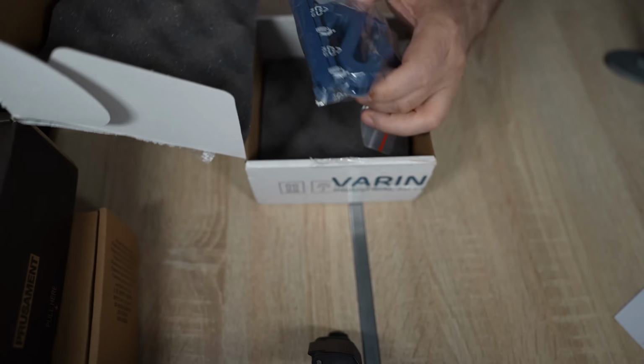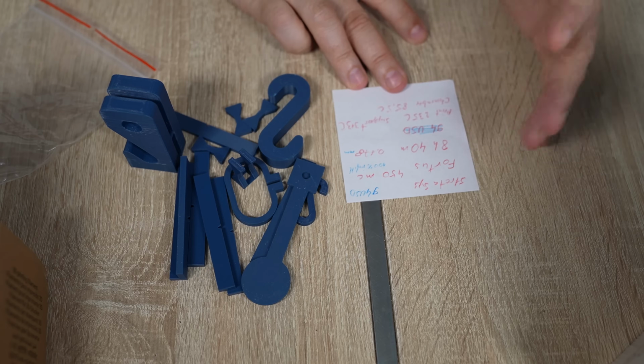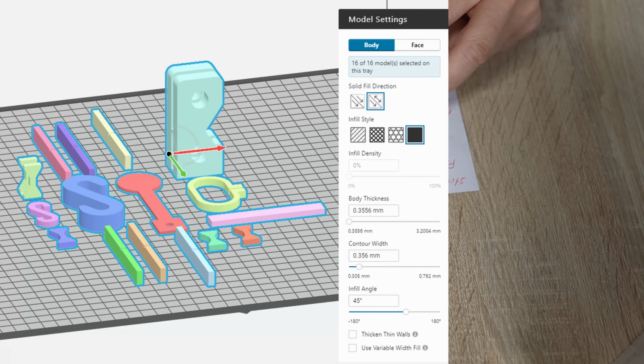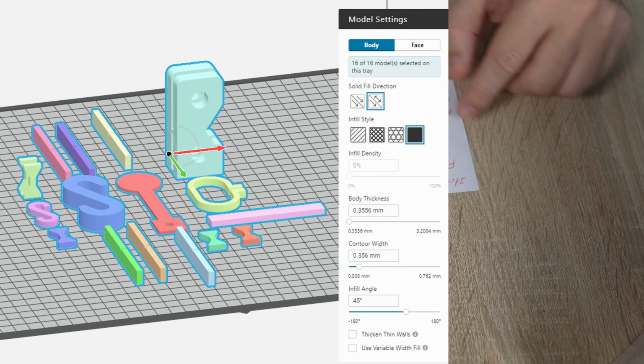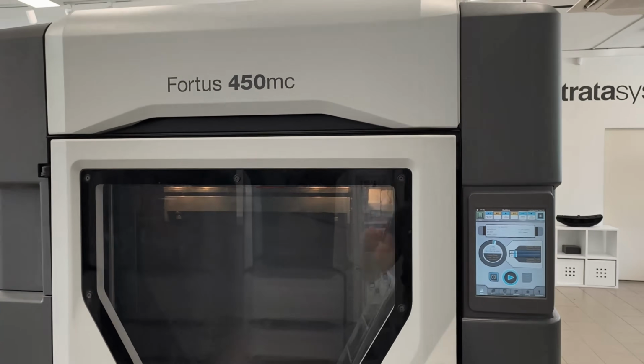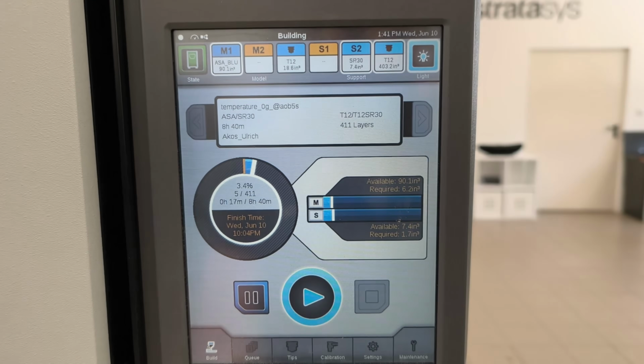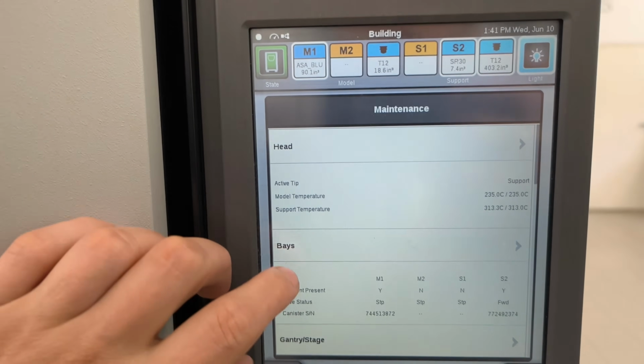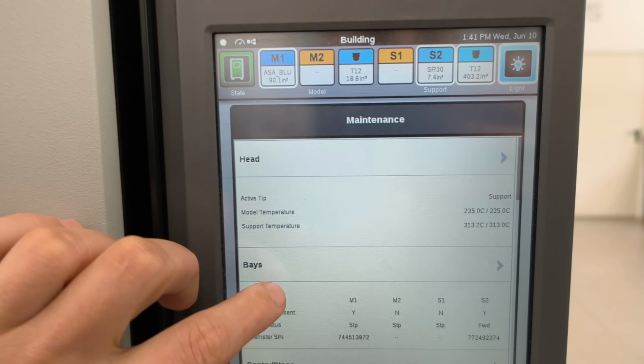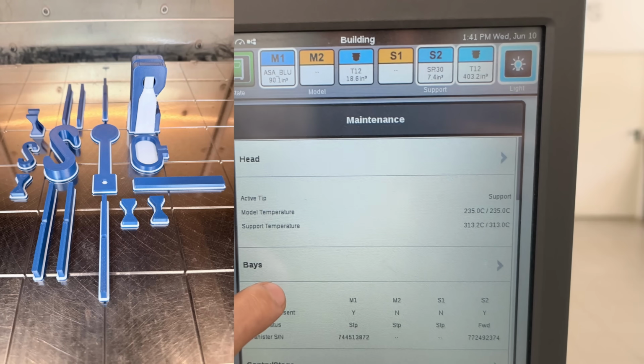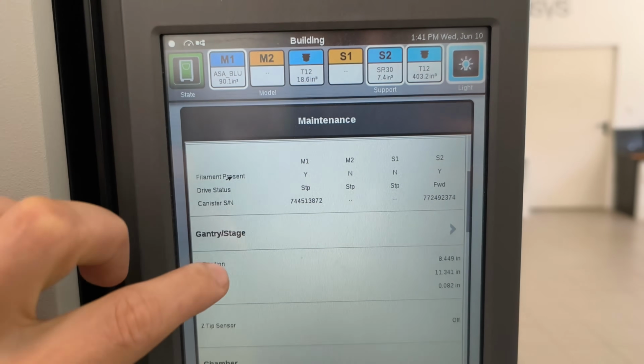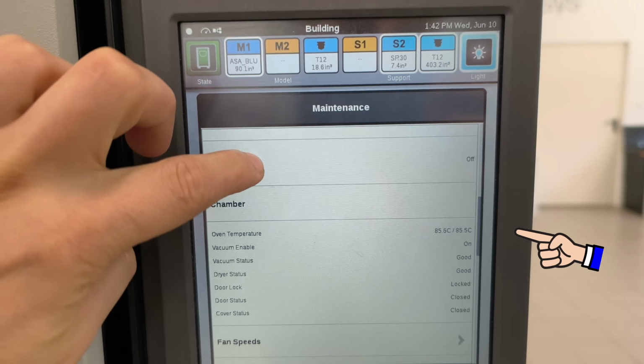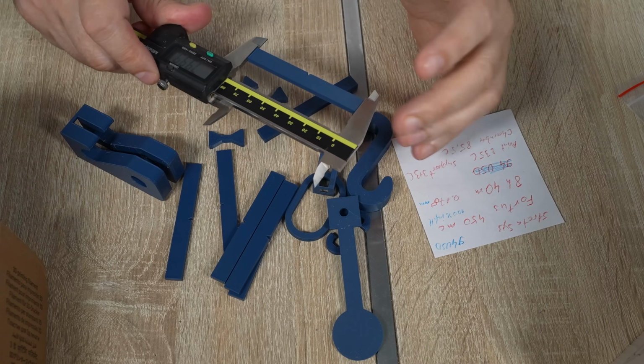A few words about the test objects. I got some pictures and footage, and from the slicer image I can see that it is printed with 100% infill as I requested, on a Fortus 450MC 3D printer, and the printing time was 8 hours and 40 minutes, with 0.178mm layer height. Interesting, the print temperature for the ASA was 235 degrees Celsius, but they also used support, and for the support the nozzle temperature was 313 degrees Celsius, and also very interesting, a very high chamber temperature, which was 85.5 degrees Celsius. The quality of this test object is great.